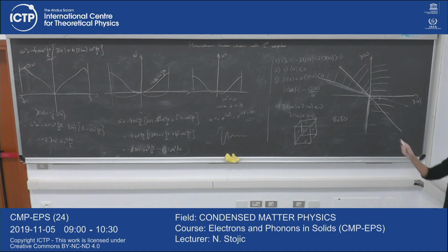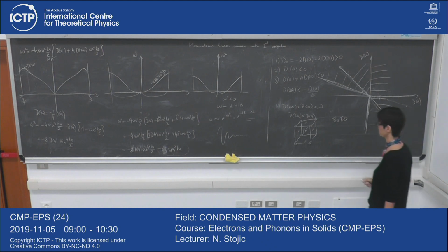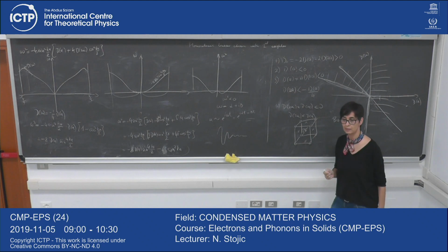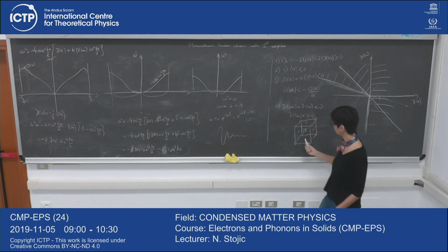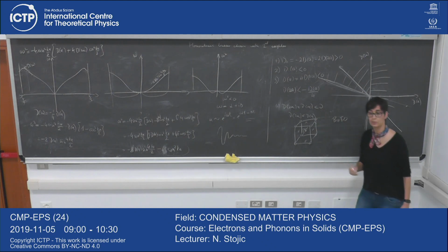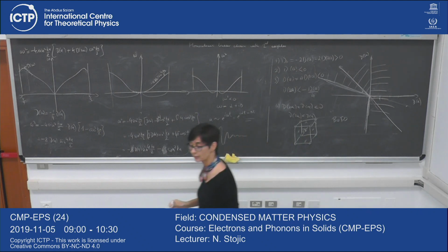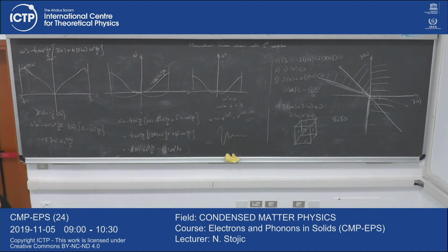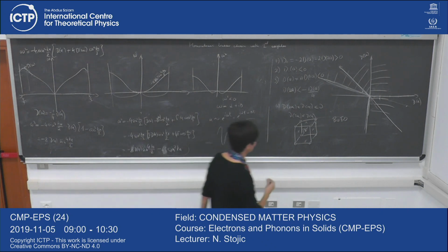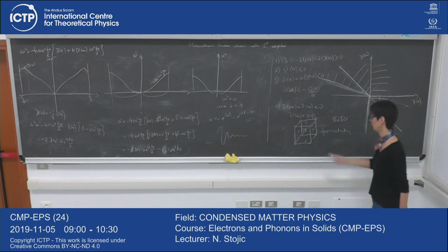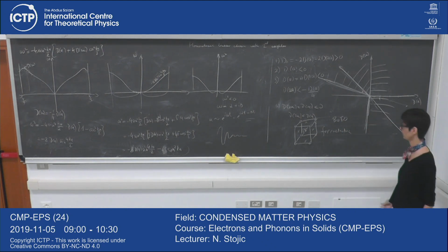Due to some of these vibrations, you will displace titanium out of the plane in one direction, and the barium in the opposite direction, and it will freeze there. It will become a new ground state. So this is the ferroelectric behavior.